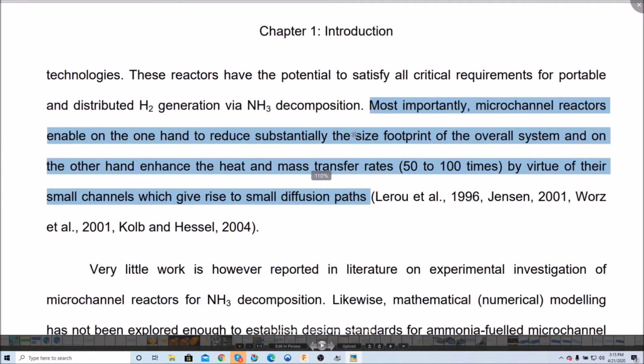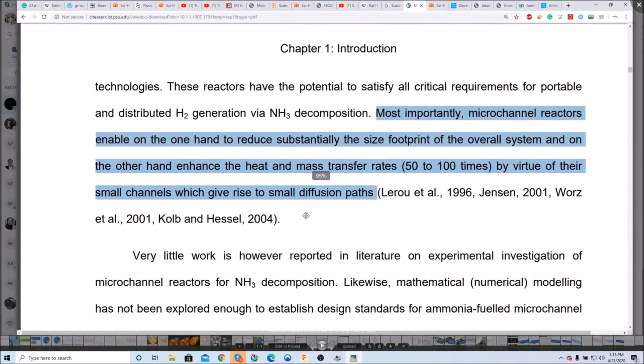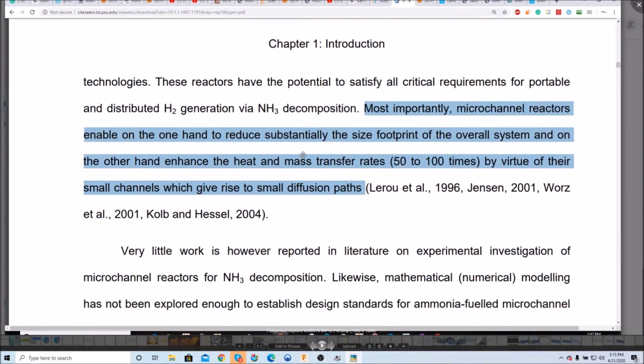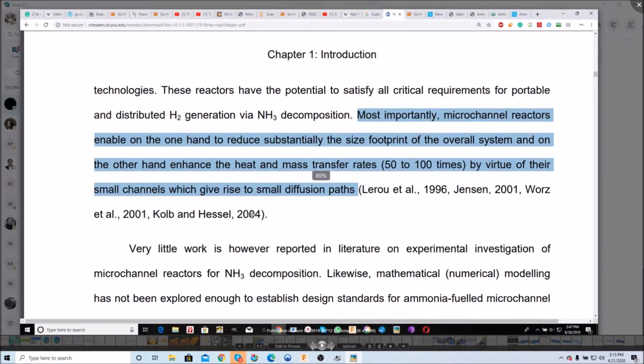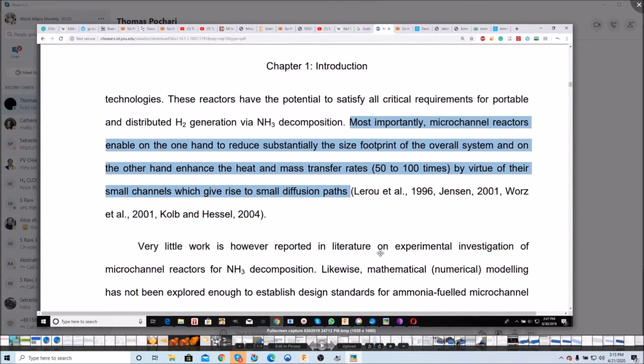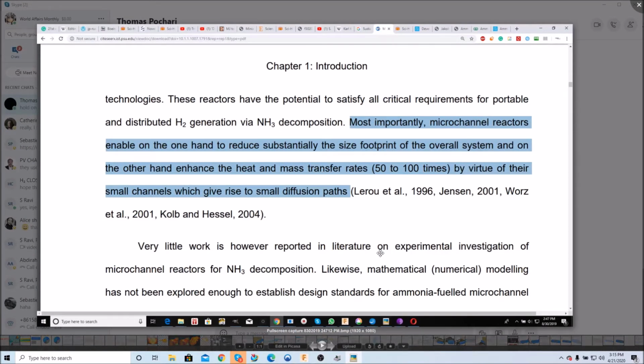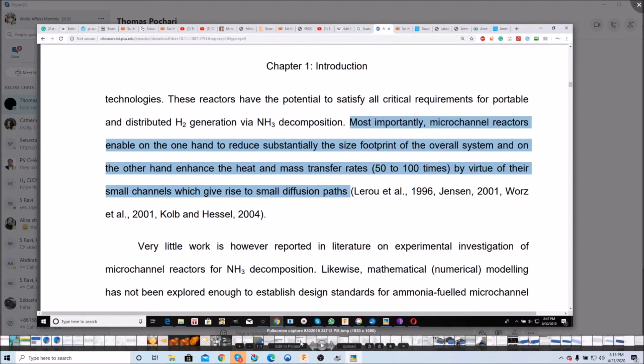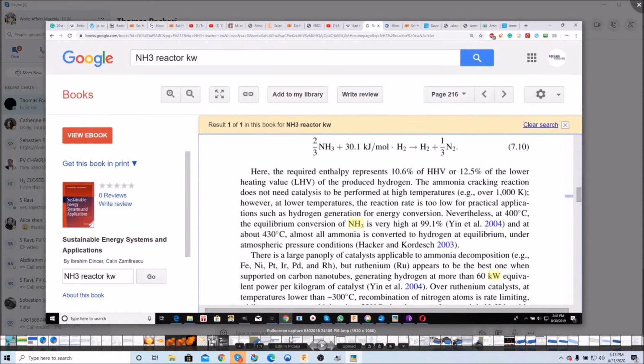Okay, so another important point, microchannel reactors have a substantially smaller footprint and enhance heat and mass transfer rates 50 to 100 times by virtue of their small channels, which essentially is about the surface to volume ratio. If you decrease the diameter of the channel to these very minute sizes, you will enable very, very high rates of heat transfer.